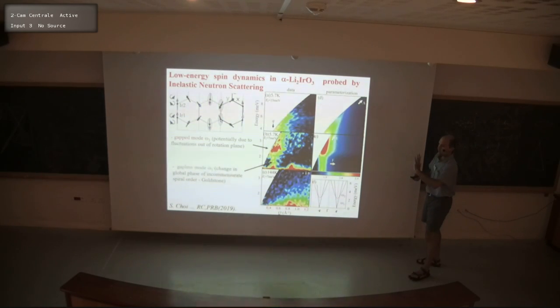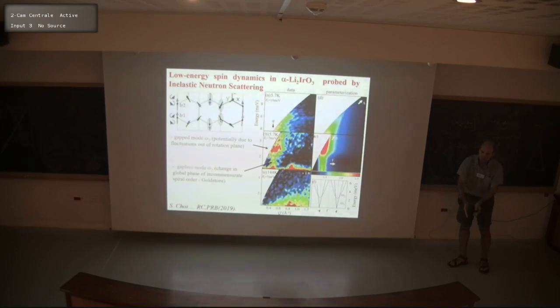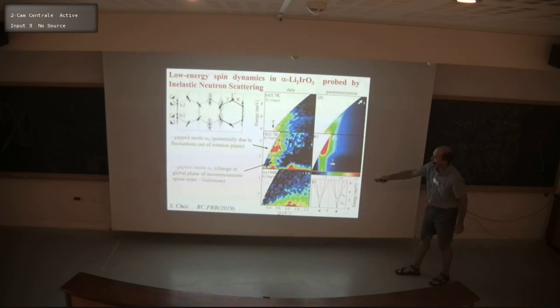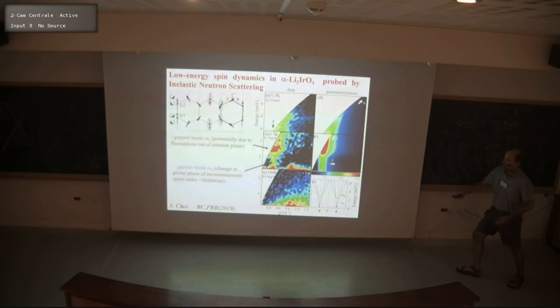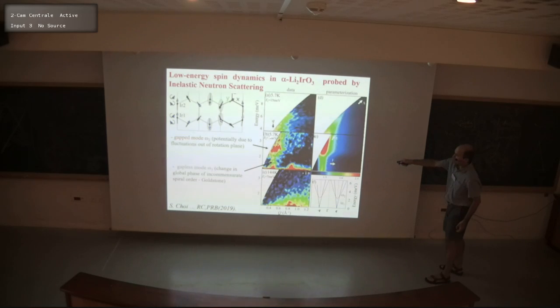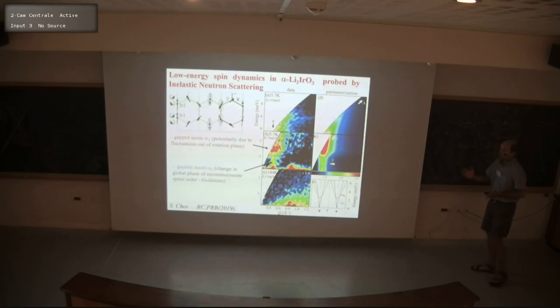And what I showed you, this animation of changing the global phase, we expect that to be visible in a gapless mode that comes all the way down to low energies. And indeed, we see evidence for magnetic scattering going down to the lowest energies that we probe. And we associate that with this Goldstone mode of changing the global phase. And then inelastically, we also see an onset of evidence for a gap mode, also above the Bragg peak position. And that possibly could be associated with fluctuations of the spins out of the rotation plane.